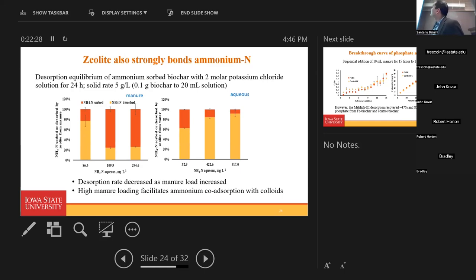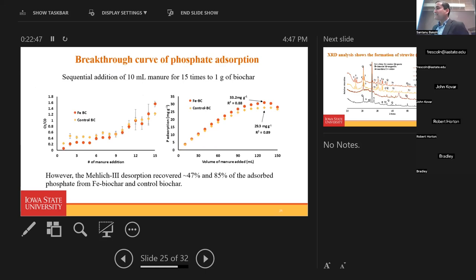This is the desorption from the zeolite with 2 molar potassium chloride, and you can notice that zeolite also strongly bonds ammonium nitrogen. Desorption rate decreased as manure load increased, and high manure loading facilitates ammonium co-adsorption with colloids. So next is the breakthrough curve.